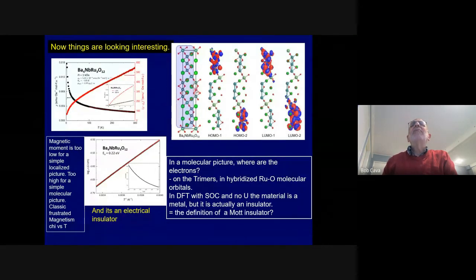And then when you try to calculate where's the spin, you discover, well, this is broken up. You can have a molecular orbital picture that shows the highest occupied molecular orbital and the lowest unoccupied molecular orbital in the trimer, and you can see that the spins are delocalized in the trimer. Now, the magnetic moment is too low for a simple localized picture, and too high for a simple molecular orbital picture. So this one is pretty wacky, and it's got frustrated magnetism, and it's an insulator. Why is it an insulator? If you do a regular DFT calculation with no electron-electron repulsion, the thing is a metal, but it's not a metal, it's an insulator. So I wonder, is this the definition of a Mott insulator or not?